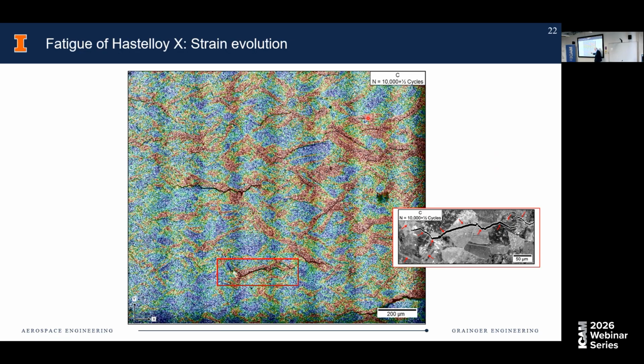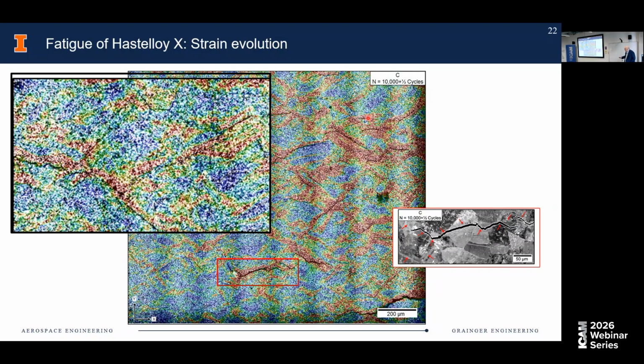And here's the close-up of that one that I showed you, with these images from the SEM. This is a very high resolution image, and I can zoom in, and it may not be exactly visible, especially with the lighting, but almost every stress concentration here has a crack in it. If I zoom in here in the upper left-hand corner, let me point it out here, right? Almost every stress concentration has cracking associated with it, and even some of the smaller ones.